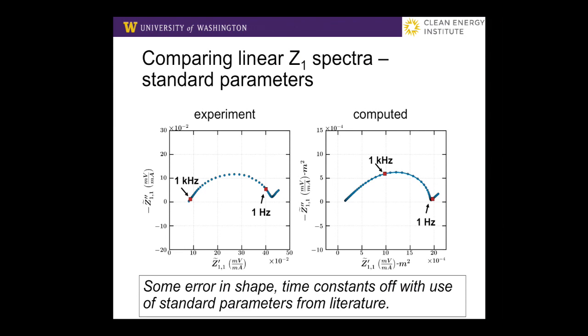So the dynamics that we're putting in using standard parameters, these are the parameters people usually use because they're thought to be the best representations. A lot of people model these kind of batteries. It's most common, really, in the literature on modeling it. We're harvesting the most common standard literature parameters, and now we're looking at them for our battery, and they're off. So we could do a best fit, even with the linear contribution. We can see that we're a little bit off. And so we could do best fits on those parameters, get 5 or so lump parameters, more information, and do a better job of fitting this, I think.